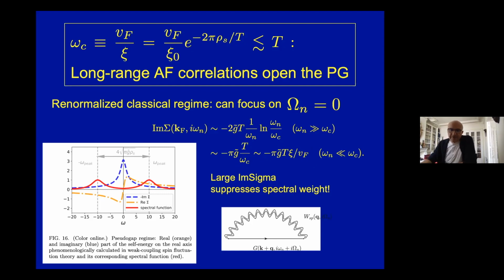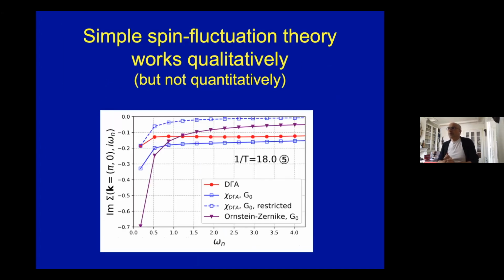And indeed, this validates the Vilk-Tremblay mechanism for the opening of the pseudogap by long wavelength antiferromagnetic fluctuations in this weak to intermediate coupling regime. So nice as it is, this analytical understanding can be compared to actual computational results. And what we see is that the simple spin fluctuation diagram actually works qualitatively. But as you see on this plot, which compares the actual results, which you can take to be this one, to such approximations in various incarnations, it doesn't really work quantitatively.